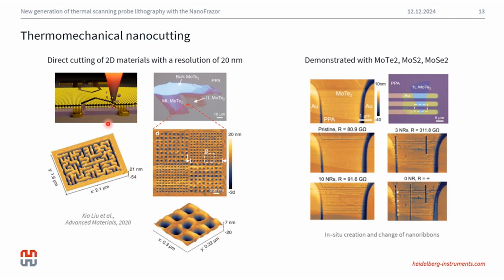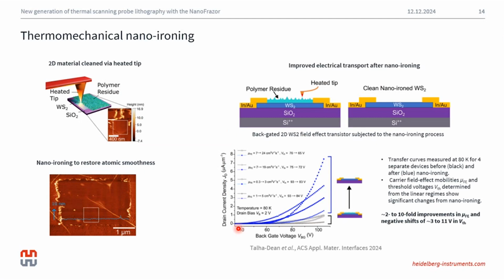How this was done is by applying the 2D material on top of a PPA layer. And when the heated tip is brought in contact with this 2D material, the PPA underneath was sublimating, which caused the top 2D material flake to break off in various shapes and forms. Aside from thermomechanical nanocutting, you could also perform thermomechanical nano-ironing of 2D materials. Here, the thermomechanical properties of the heated tip are used for nano-ironing of very thin films, and this technique was used in particular to reduce the impurities and defects on top of the 2D materials, which led to the boosting of their electrical transport performance and making them even more efficient for advanced applications like quantum computing.